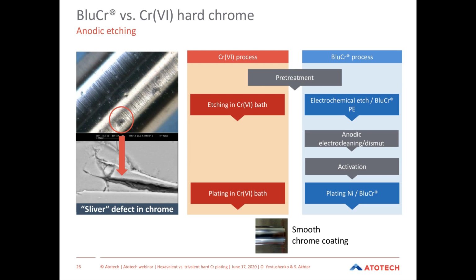But to overcome these issues, we have the solution, and this is an electrochemical pre-etch for the parts which might have these problems. And in this case, yes, it is an electrochemical process. After that, you might need to apply anodic electrocleaning, the so-called desmutting, then activation, and then you go subsequently for nickel and blue chrome plating, and at the end we are able to achieve the same results as in the case of etching in chromic acid. So smooth, nice deposits are achieved at the end.